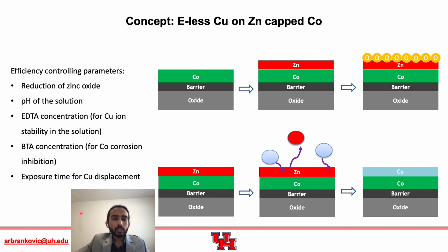So once the surface of this zinc is reduced and once we have metallic zinc present on the surface, we bring this sample to the aqueous-based solution which contains copper ions. At this point, there would be galvanic displacement between copper and zinc, and as copper being more noble than zinc, it would displace all of the zinc from the surface and deposit here.